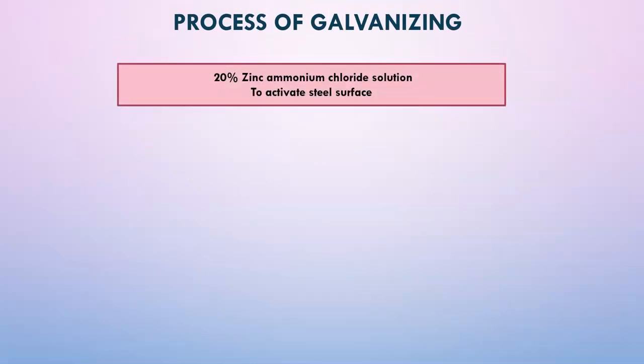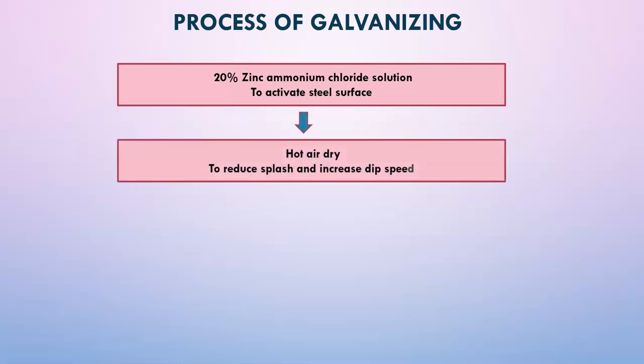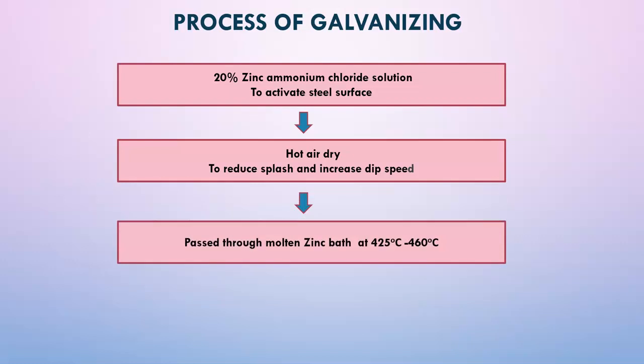Let us see the process of galvanizing. The prepared sheet is dipped into a bath of zinc ammonium chloride solution. It is then dried with hot air and then dipped into a bath of molten zinc, which is maintained at a temperature of 425 degrees Celsius to 460 degrees Celsius, little higher than the melting point of zinc, which is 419 degrees Celsius.